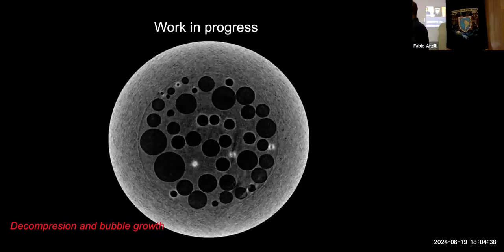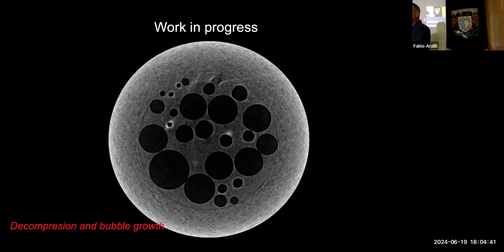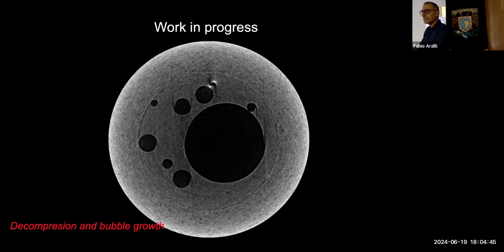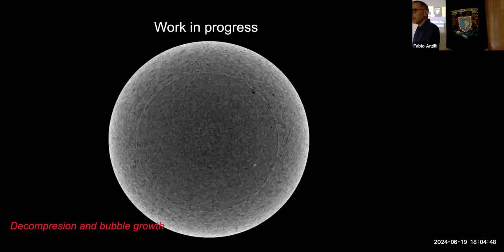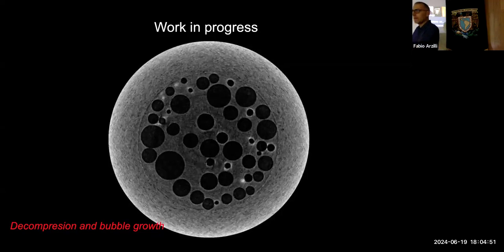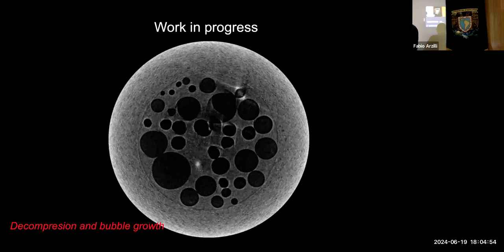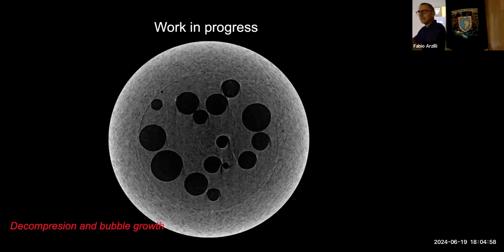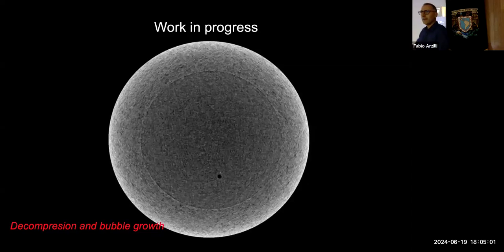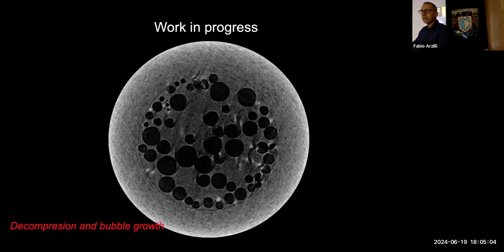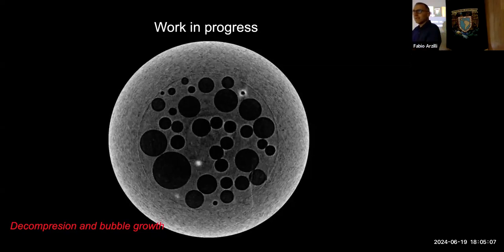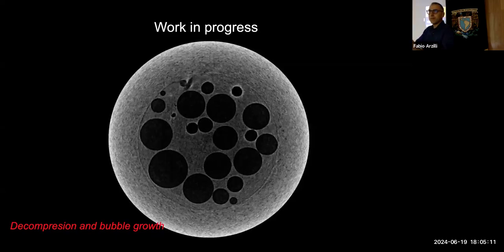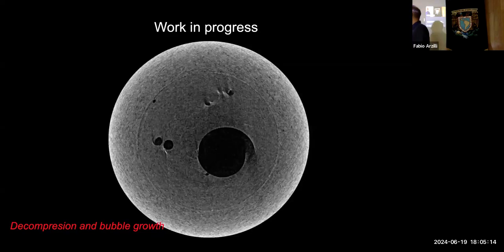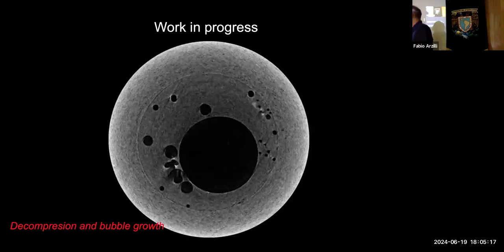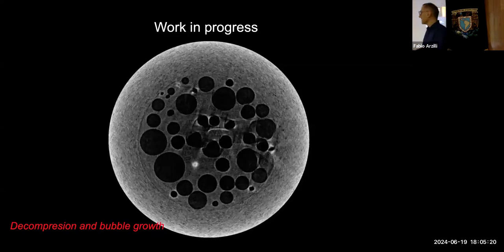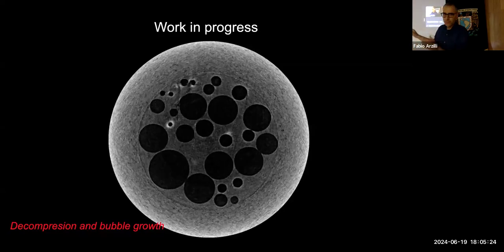This is an important aspect because during magma ascent, coalescence of bubbles can determine if the system is degassing, but still the bubbles will be coupled with magma, so you don't have outgassing, and this will maintain a lot of energy during ascent and will accelerate the magma ascent, compared to if you develop a network where at the end the permeability will be dominating, the gas permeability will be developed basically, and the conductivity. This will determine basically outgassing and possibly decoupling between gas and magma. So these experiments were performed with this idea.